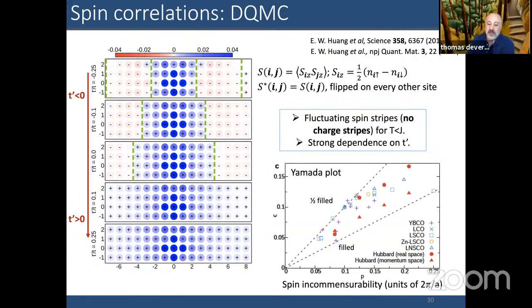And if you plot this incommensurate spin incommensurability as a function of doping, the simulations can be looked at from either real space or momentum space cuts, so-called MDC or EDC, to determine that value. And that's plotted along with some data. So it lies somewhere in between half-filled and filled stripes, maybe closer to half-filled than filled. And its doping dependence doesn't seem to be special to 1/8 doping. It seems to be there for doping even up to 20-odd percent or so.